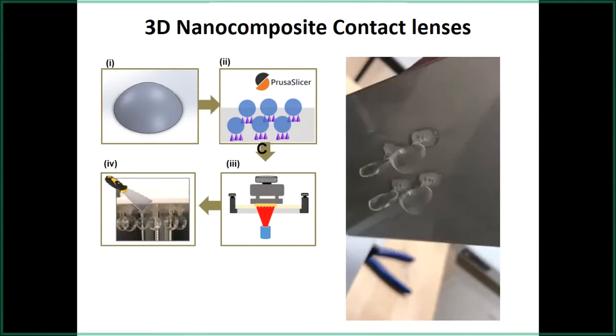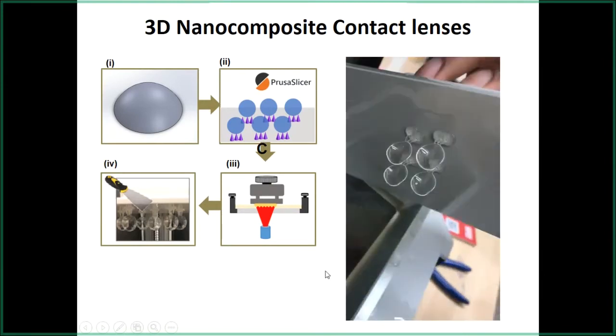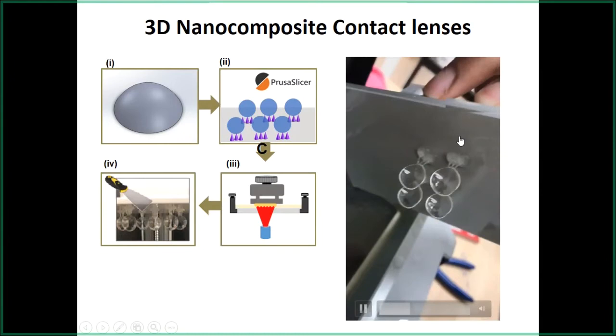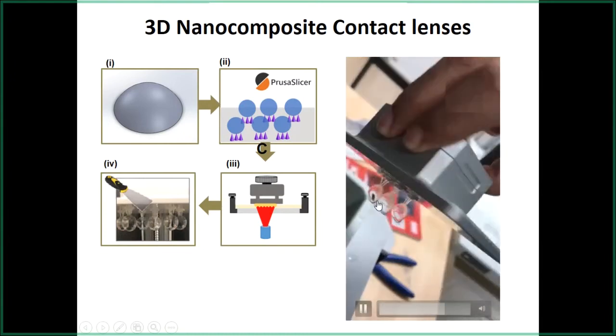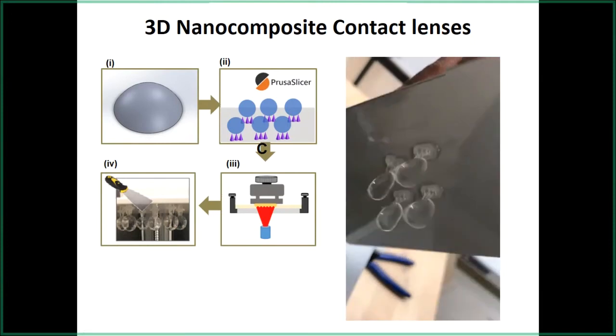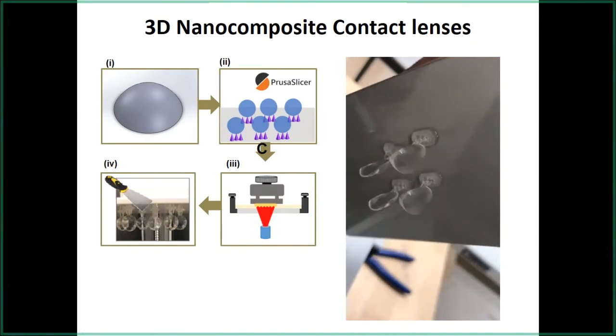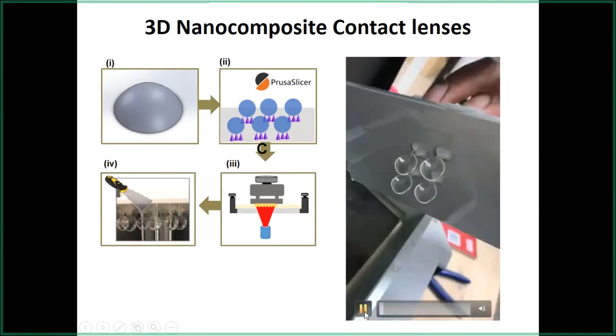One thing is just the geometry and then printing it, but it's not as straightforward as that. You can also see the contact lens have been printed vertically. There is a lot of trial and error that went into this. So now we have the complete recipe of making these contact lenses. After something is 3D printed, it's very hard. So this also means that we have tried a lot of materials. Most of the reagents that we used were toxic, so they are not applicable for contact lenses. And all other reagents, once they are cured with UV or 3D printed, become very hard. So you can't call them contact lenses, whatever structure gets printed. So that's why we have used our own materials and optimized their recipes as well.